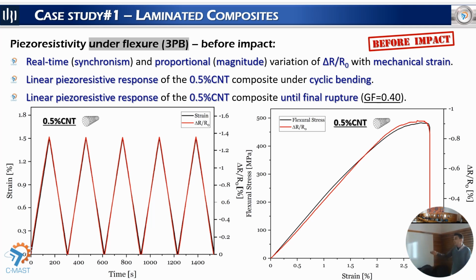It means that there is a real-time synchronism between the mechanical signal and the electrical signal, and this is exactly what we want to achieve: a good relation between the mechanical deformation and the electrical variation that can give us an idea about the deformation that is being imposed on the structure. This good relation was observed in cyclical tests, but also in monotonic tests till the rupture of the sample.